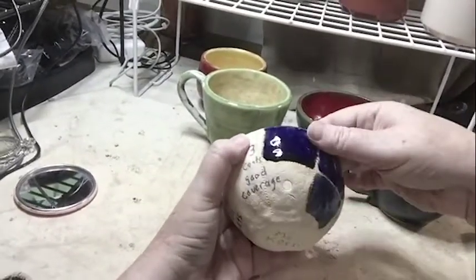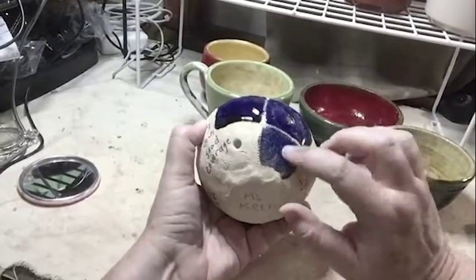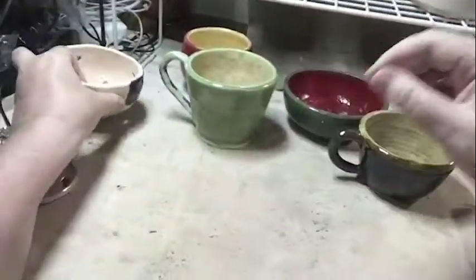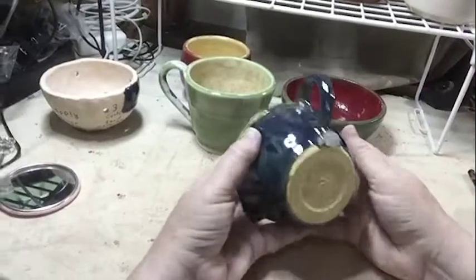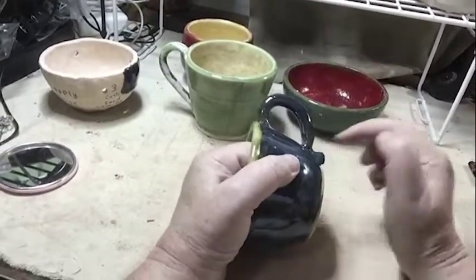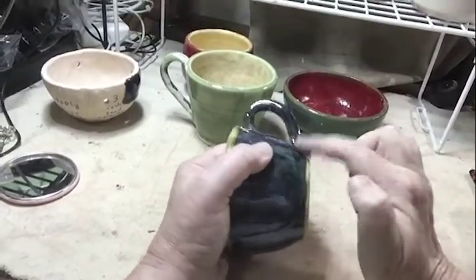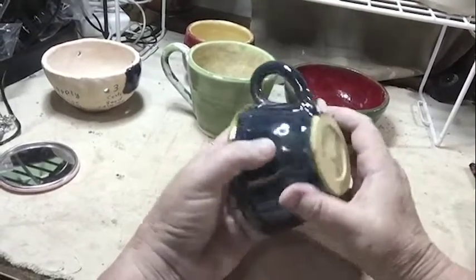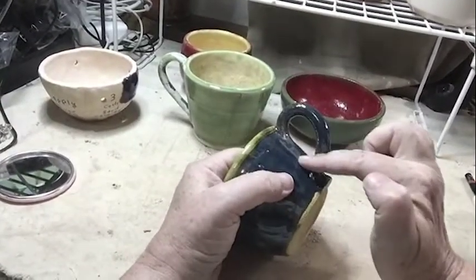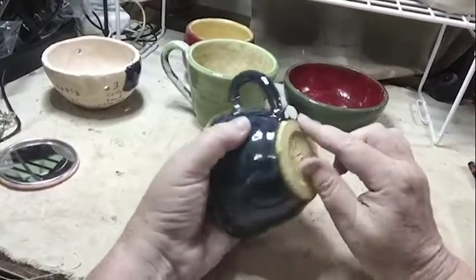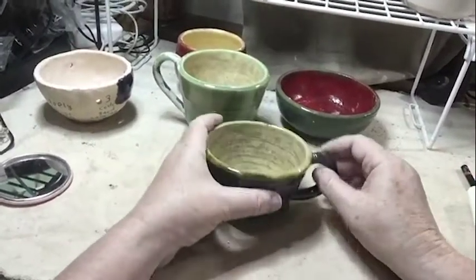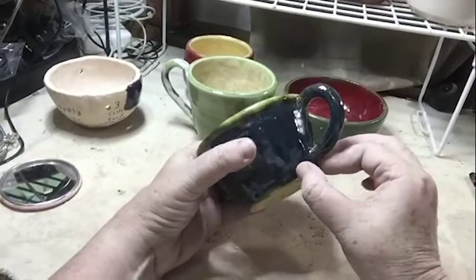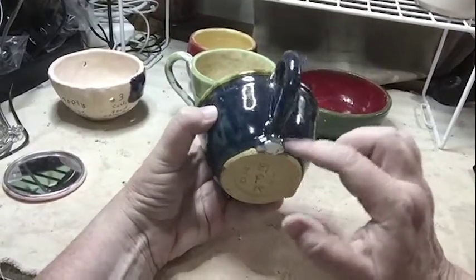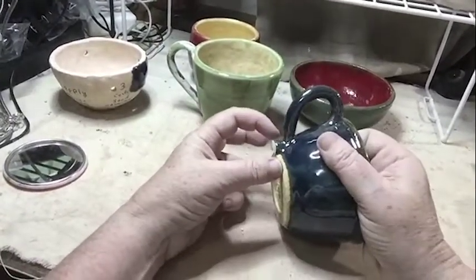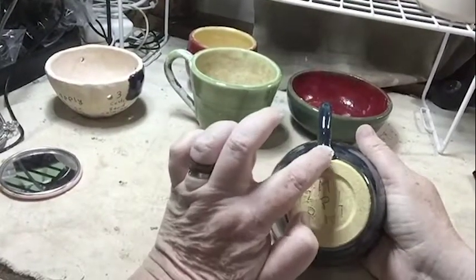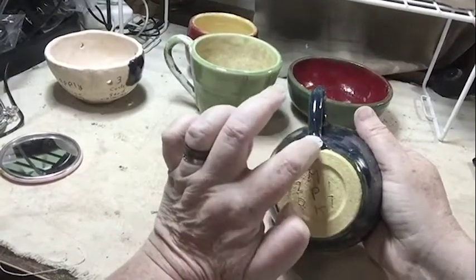But if you have an over thick application, so we've talked about under applying and getting a thin application, if you get too much glaze on there, you can get this problem. Okay, so this is where I applied a very heavy, very thick coating of glaze to the point where it ran down like a huge teardrop, and then where it was sitting on the kiln shelf in the kiln, it just pooled there and created this big error right here. Okay, a big drop that had to be hammered off of the kiln shelf. So you don't want to do that.